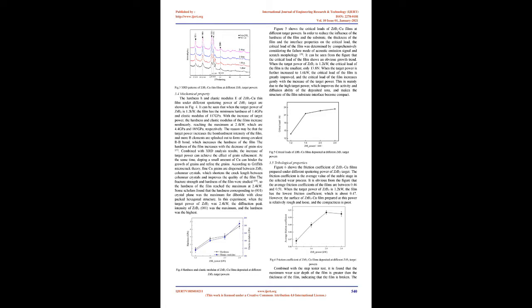According to the related theory of thin film growth [21], when the power of the ZrB2 target is high, because the energy of incident particles exceeds a certain threshold, the implantation effect occurs. At the same time, the collision between ions heats the gas on the target surface and dilutes the ion density, which reduces the sputtering yield and limits the increase of deposition rate. Fig. 1 Deposition rate of ZrB2-Cu thin films deposited at different ZrB2 target powers.